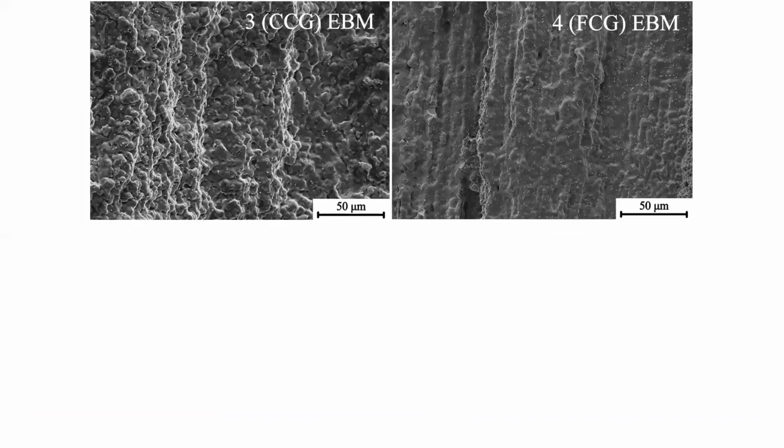The cracking mechanism was confirmed with the aid of opening up the crack face together with SEM fractography observation. The presence of a liquid film on the crack face suggests that solidification cracking is the mechanism. This also means that the precise parameters related to SEBM were not at their optimum condition in terms of the solidification from the liquid to the solid phases.